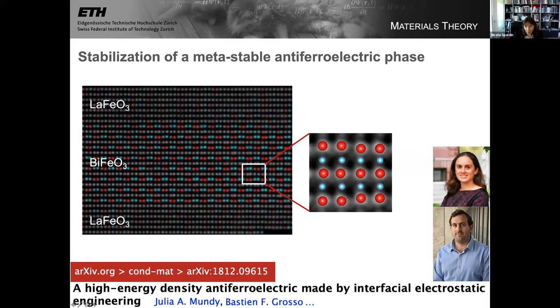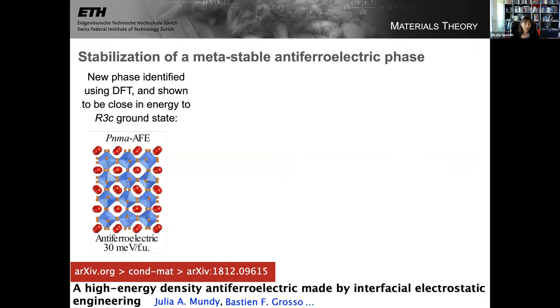The blue circles are the iron ions. Then we have a row of bismuths not going anywhere, and then a row of bismuths where two go down directly below the two that went up before, and then two go up where the two went down before. And so Julia came to us and said, well, what on earth's going on here? They had these microscopy images, but this kind of pattern of bismuth displacements did not correspond to any known phase of bismuth ferrite.